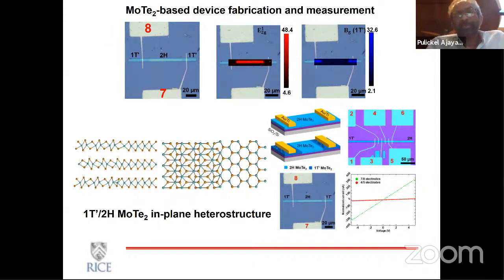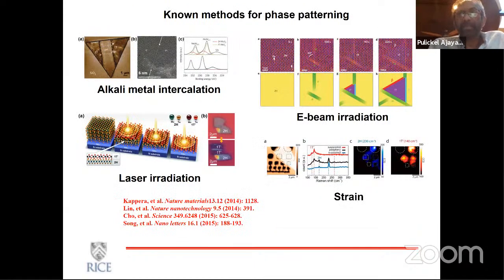But of course, it would be much nicer if you can controllably create these in the locations that you want. For example, can you create a molybdenum telluride structure and then go around using some kind of stimulus to change it to a 1T prime? Then you know exactly where you put the contacts rather than going and searching for them. And as you can see, there are so many high impact papers based on this idea of locally changing or phase patterning, essentially.